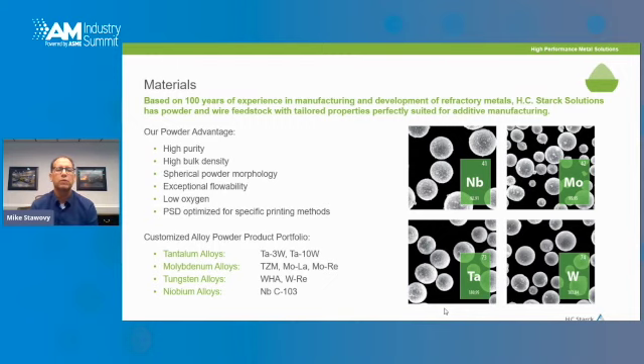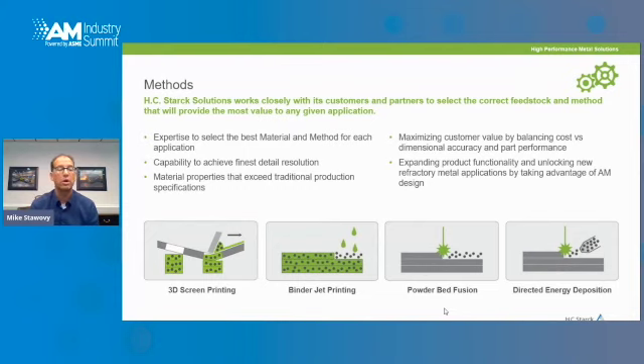But I think something that's unique with HC Starck is we're able to make refractory alloy powders, and I think that's something that's less common in the industry, even in the refractory metal community. So in some cases, we've done printing trials and built parts from alloys such as tantalum with 3 weight% tungsten, tantalum with 10 weight% tungsten, some molybdenum alloys such as TZM, which is a zirconium and titanium alloyed molybdenum material, molybdenum with lanthanum oxide, molybdenum rhenium, as well as tungsten alloys such as tungsten heavy alloy, tungsten rhenium, and a niobium alloy called C103.